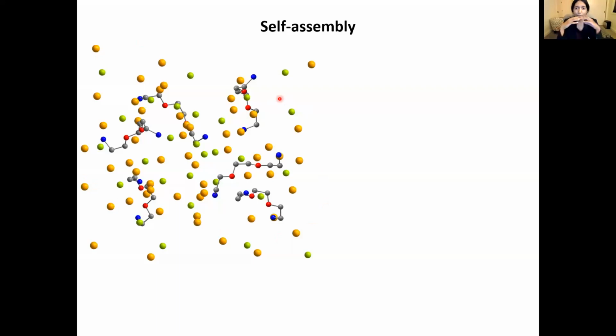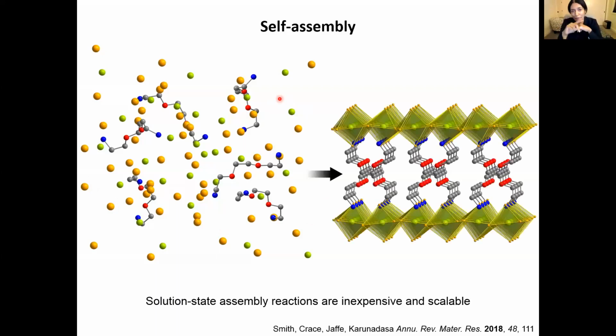And our job is to try and persuade this big mess to form these beautiful ordered structures. And they have to form of their own accord. So we don't force them. I like to say we persuade them by changing the crystallization conditions. The challenge of self-assembly is that 100 different structures can form. So how do we get these ions to form the particular structure we want? The beauty of self-assembly is that once those conditions are identified, you can make the same structure every single time. You can scale it up, you can make grams of this stuff, you can take a solution and deposit a film of this material on any substrate, which is really important for making devices. Everything is cheap and scalable and reproducible.